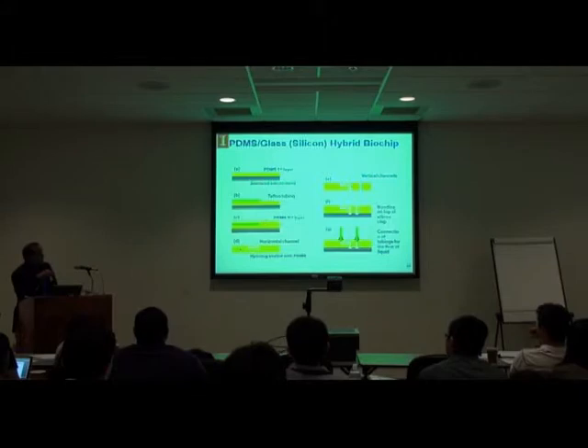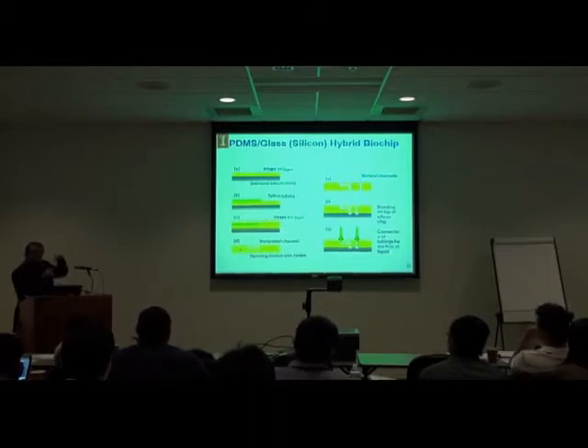Then you might take another physical structure, like even a little Teflon tube, for example, and use that tube as a mold, essentially, and then put a second PDMS layer, and then now you can pull this tube out, and you'll form a channel. You can even close the end of the channel by putting a little drop of the PDMS and seal that. You can form vertical channels. We often do this by actually putting a PDMS around a Teflon tube that's vertically attached.